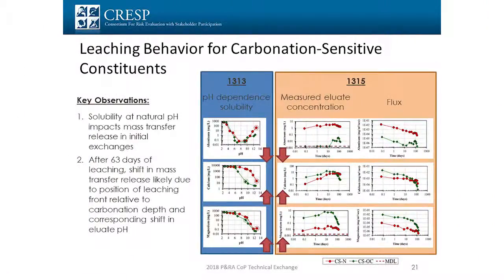Other effects, and again, this is on the cast stone material. You can see some effects based upon whether you're carbonating or oxidizing on both the pH-dependent test and the mass transfer test. You can see the change from carbonation will affect the solubility at the natural pH, and that is, in the leaching world, where you don't add any acid or base to control the pH level. You just let it go where it wants to in terms of the leaching itself. You can see it affect the initial mass transfer releases because of this effect on the natural pH.